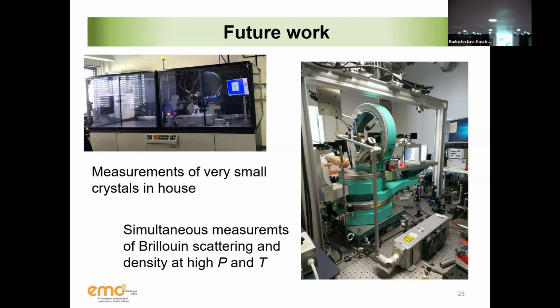Yeah, the problem is that, for example, for garnet, garnet is always a problem because they put your velocity down. So when you get a global model, your velocities are always lower. Marta actually showed it in her thesis that we had too low velocities. But if at high temperature, if we are correct, those were underestimated, so this difference may not be so large. I see.